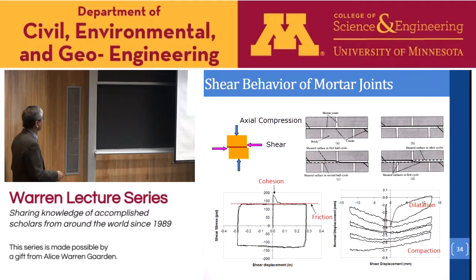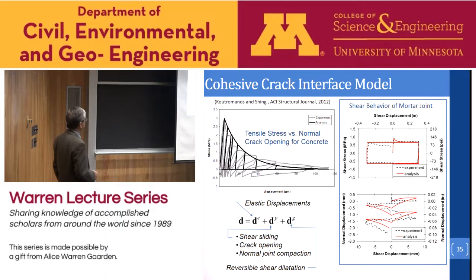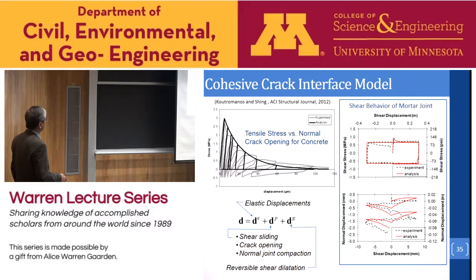So we developed an interface model which can capture this behavior. It's a very simple interface model, capturing this shear and joint dilatation, and also tensile crack opening and closing behavior in a very simple way. And in this model, it's an elastic plastic formulation. So we have an elastic component. We have a plastic component which accounts for shear sliding, crack opening, and also joint compaction, and a geometric component which accounts for the joint dilatation. So I will just quickly go through. I'm not going to elaborate on that.